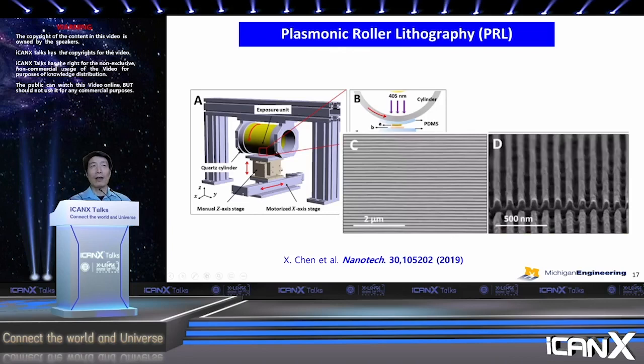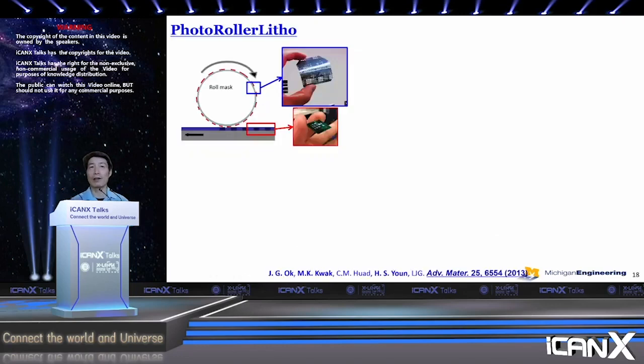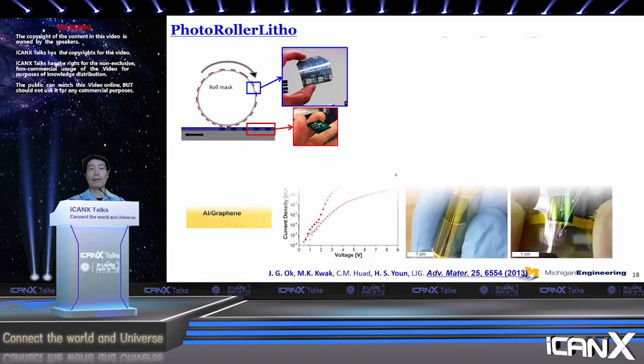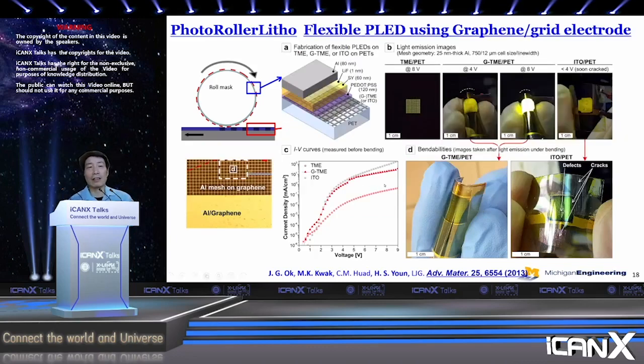Now, this is for very small features. Sometimes, let's say for a touch panel, the feature size doesn't need to be that small for the touch circuitry, so you don't have to resort to this sort of technology. You can use a simple ordinary photomask through roller photolithography. Just make a flexible mask around your quartz tube and shine the light through it, and you can do it. Previously, because this is a very gentle process, you don't have to imprint into your material. In our case, we demonstrated a pattern on a layer of graphene. Graphene itself is not a good transparent conductor, because it's too resistive, even with doping.